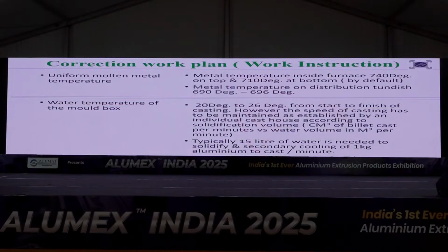Uniform molten metal temperature. Whatever is there in your furnace doesn't matter. It matters the most in your casting tundish. You design or you locate your furnace at a distance so that when it reaches your distribution tundish, it should not cross 695, 696 degree. Just that margin, your casting quality will be better.